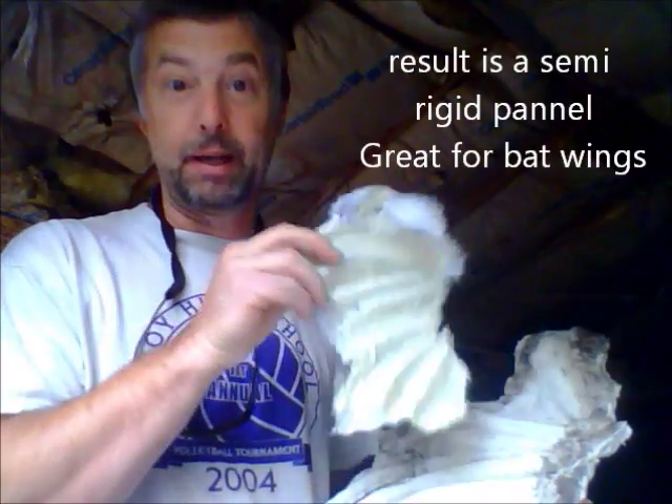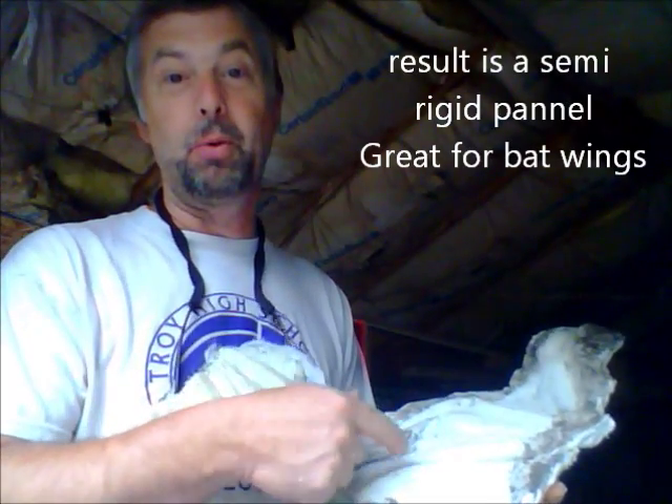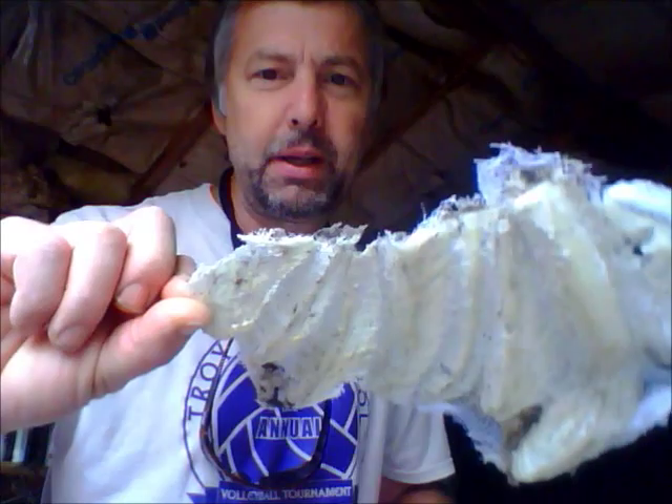So you better have some good parting compound in your mold, because I actually pulled little chunks off my mold because I didn't prep it properly. See that? And it's holding its shape. If you wanted to do tall faces, it's really tempting to just spray it full of foam and then wait. And guess what happens? Pop it out, it shrinks — it's going to look like crap. And sometimes when these shrink, they don't shrink just a little. They shrink like half their size.